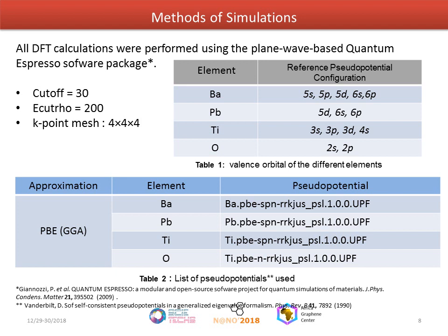This cutoff criterion has also been employed to fit the DFT calculations using the ultrasoft pseudopotential library as shown in Table 2. As for the valence orbitals, we worked with the valence orbitals mentioned in Table 1, and a k-point mesh of 4x4x4 was determined to be sufficient for sampling the Brillouin zone.